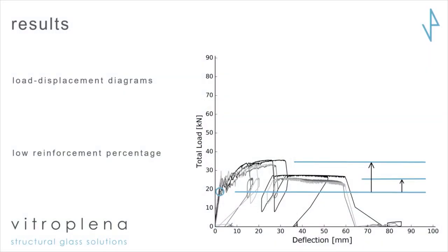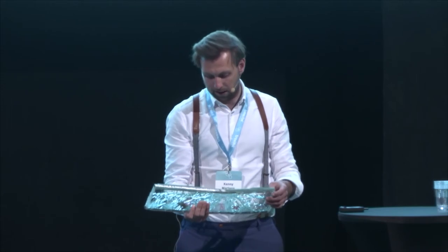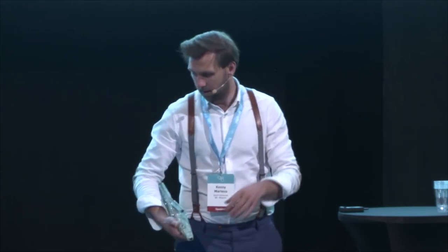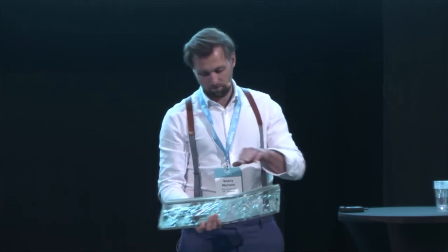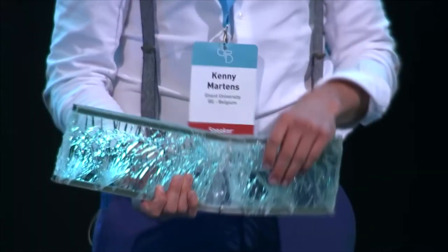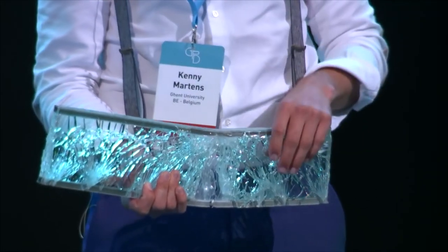These were the results. We have initial fracture where you see the circle, and again our ductile phase where loads can go up. This is for the low reinforcement percentage — this is the low-reinforced section. This is the load-carrying behavior: we had glass fracture at the point load, we go up, we have ductility, and we can carry the load almost until 36 to 37 kilonewtons.